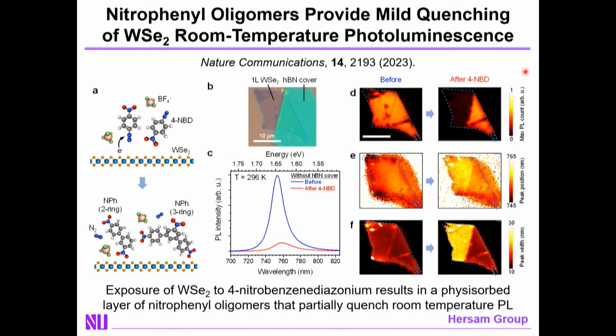Okay, so I suggest that this might be useful in the realm of quantum information sciences. And if you look in the world of single photon emitters, the most popular 2D material is tungsten diselenide. Tungsten diselenide, if it's appropriately strained and has appropriate defects, will show single photon emission. The question is, what if you form a mixed-dimensional heterojunction between tungsten diselenide and some organic species? In this case, the organic species we're looking at are nitrophenyl oligomers. These are oligomers that are formed from the polymerization of nitrobenzene diazonium, which is a famous chemistry for functionalizing carbon nanotubes and graphene. At room temperature, the effect is pretty similar to what I showed you for the phthalocyanines. You get mutual photoluminescence quenching and therefore a reduction in the photoluminescence at room temperature.